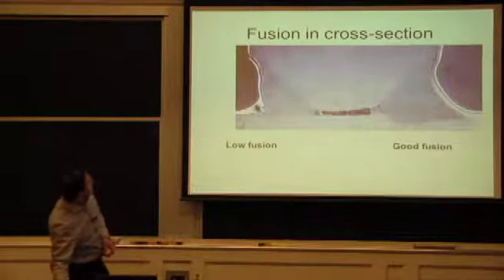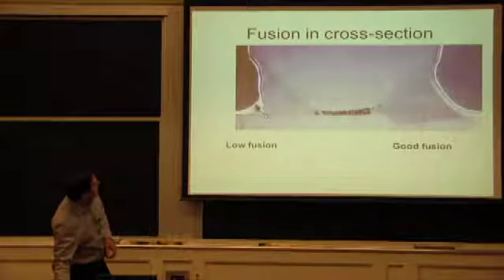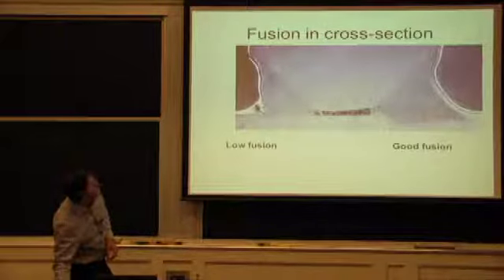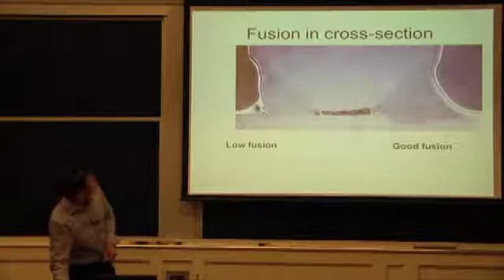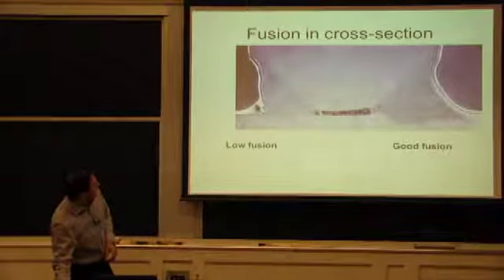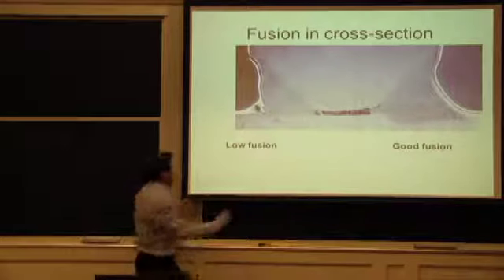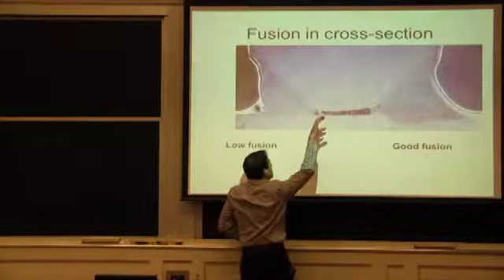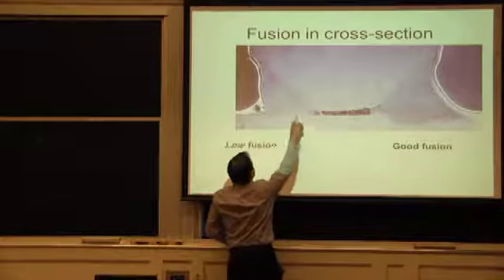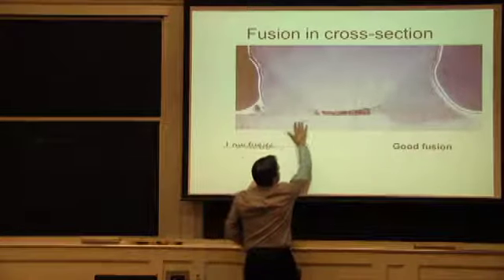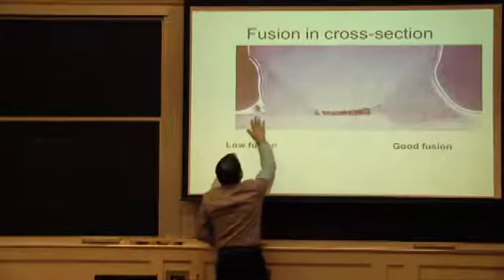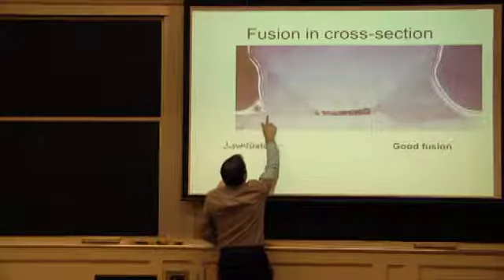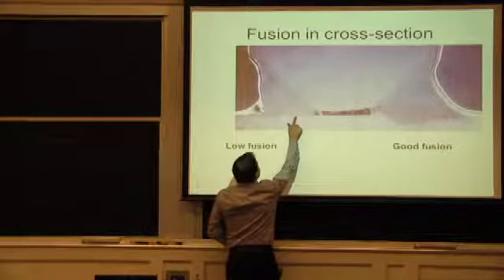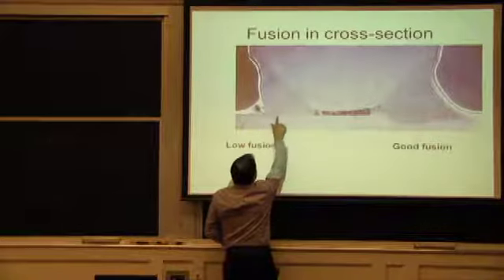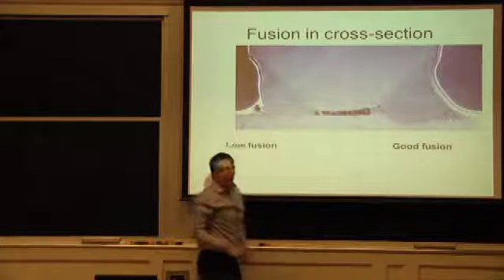And we had some cross-section views of this. You can see on this side the contact angle, between this location and this, is less than 90 degrees. And you see the interface right here. So it's not fused. This is the diagonal that has a little bend with a flat portion to be welded. And you have this lower chord of the joist. And right here, you have a little bit of grab. But look, if you start cracking right here, it will pull right off.